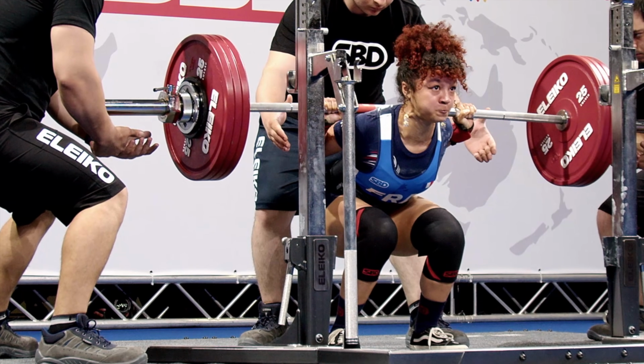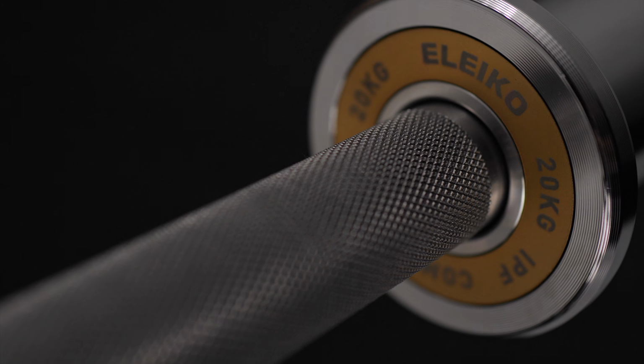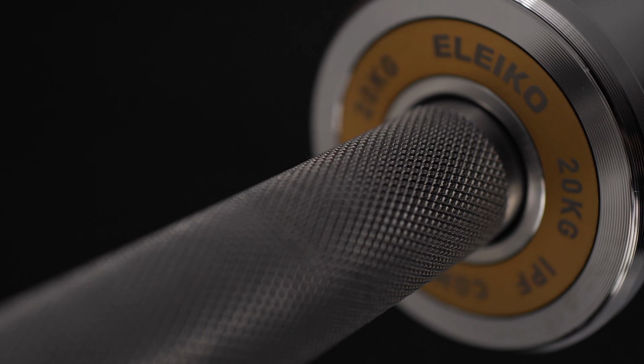We offer multiple knurling types because of the different demands in the different use cases. While we're still following the previously mentioned logic that competition bars should have the sharpest knurling, there's more to it. Because of how the sport of powerlifting is performed, the knurling on powerlifting bars benefits from having a deeper volcano knurling but fewer peaks per square area. That tends to provide the best possible grip when performing slow grinding singles in squat, bench and deadlift. And similarly, because of how the bar is moved in weightlifting, the demands are different. Here we benefit from having a not as deep but pyramid-shaped knurling with more peaks per square area. When volcano knurling is used on the multipurpose bars, this makes the 1.0 knurling mild and suitable for high training volumes without tearing up your hands or neck.